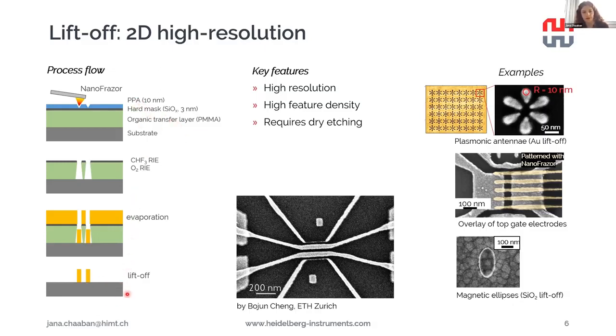And in doing so, we can carry on with our liftoff process. And you can see how much finer features are then readily patterned. We can use this technique to lift off different material systems. In this case, I show an example of plasmonic antenna, which were produced using this pattern transfer technique by lifting off gold. It's also possible to lift off dielectrics, as you see here. And it's also possible to perform this liftoff on top of pre-existing topographies. So I'll come back to this idea a bit later.